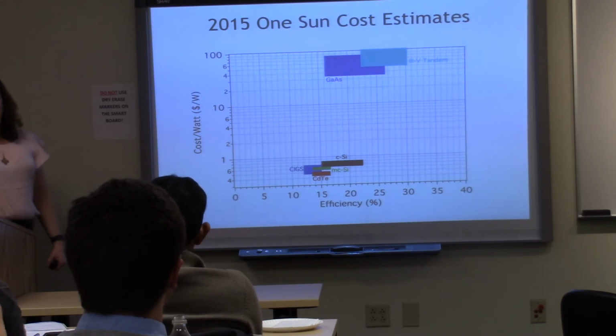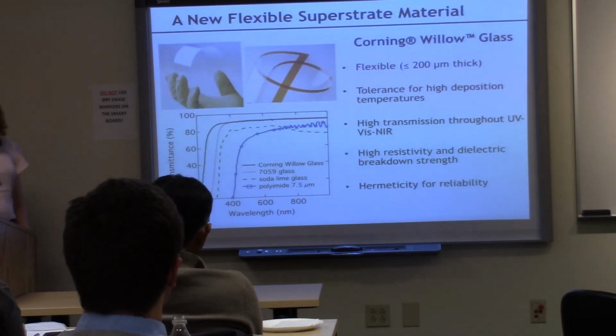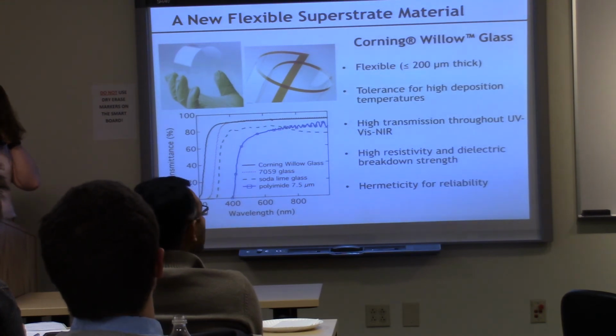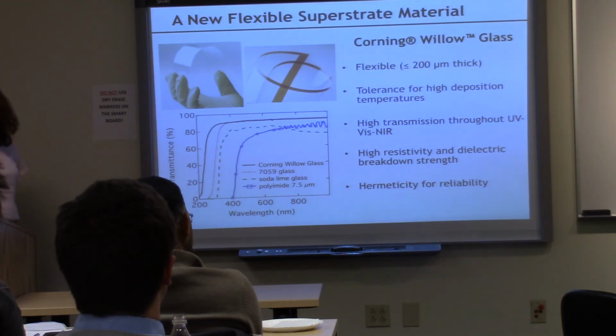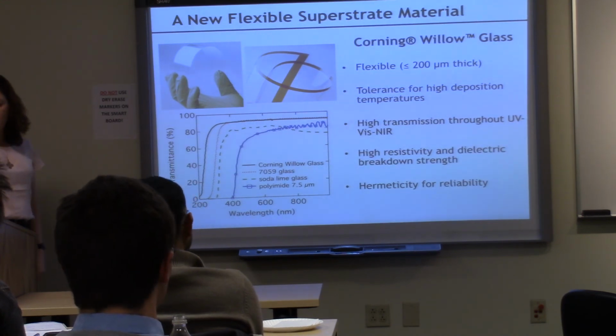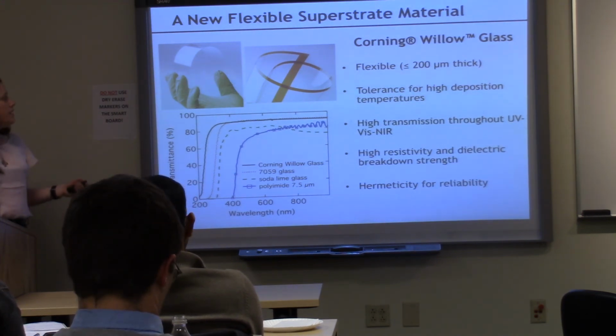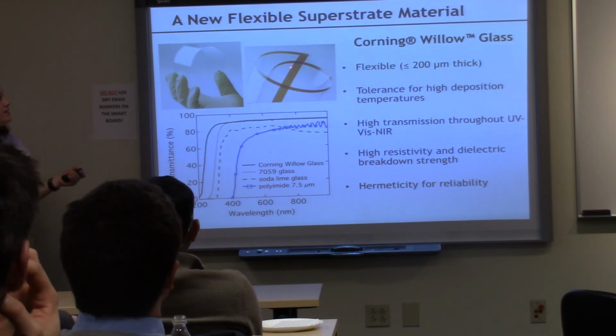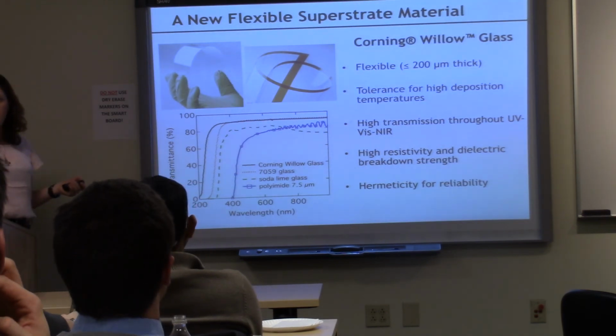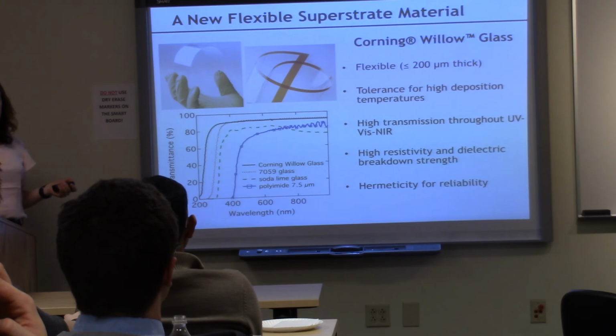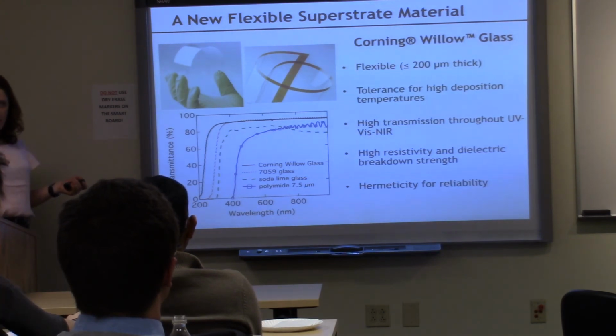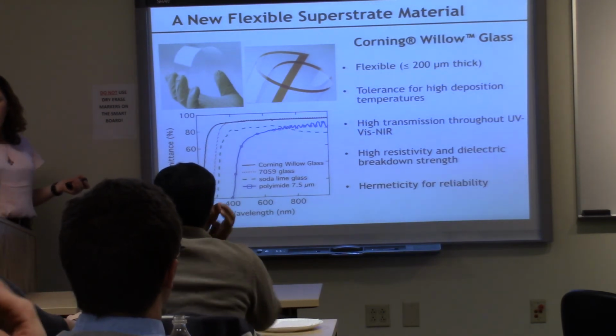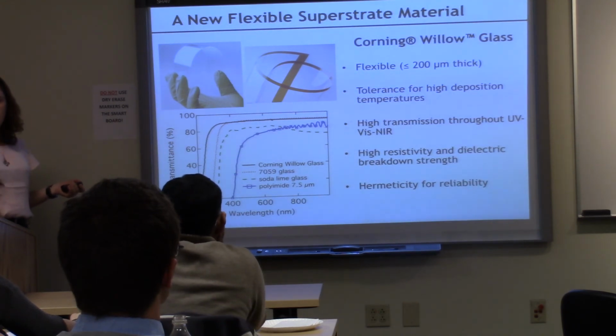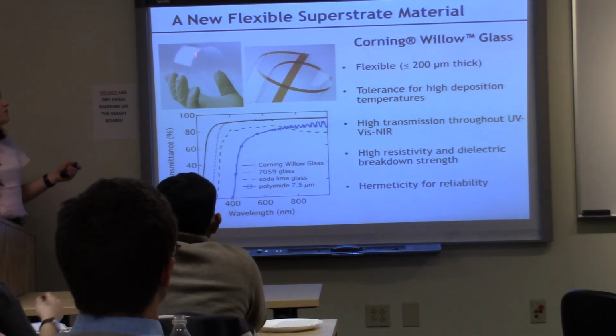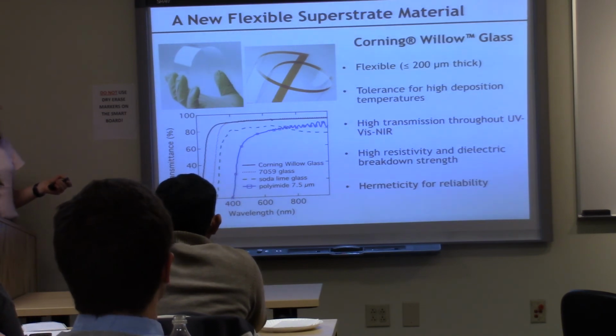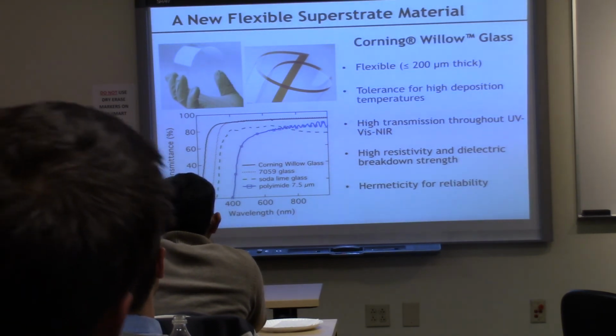When we look at superstrate materials, Corning came out with Willow Glass maybe 6-7 years ago. This is a new material. Here they put Kapton tape around the edges of it so you can see it. This is what we call a technical glass. It doesn't have any of the stuff in it that makes the TEC 15 that you guys use look kind of green, which is from iron. It doesn't have any sodium in it. It doesn't have stuff that's going to diffuse out. So it is really, really clear. They make it in a couple different thicknesses. We usually use about 100 micron thick.